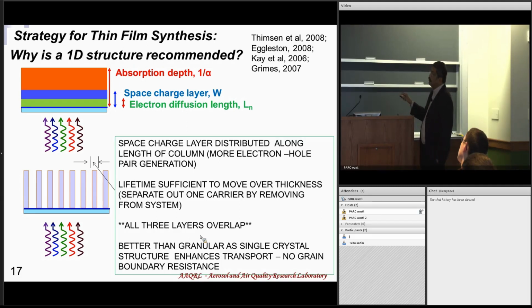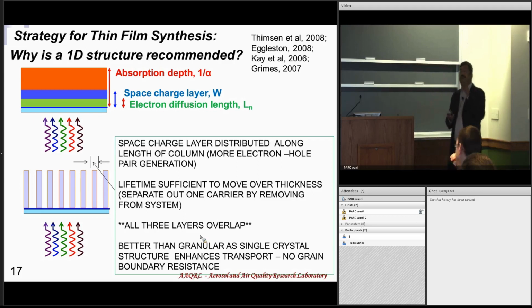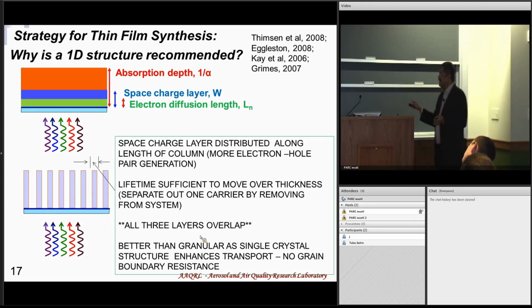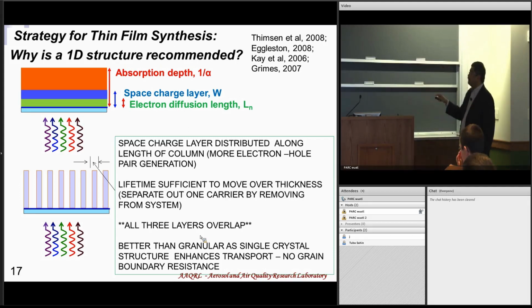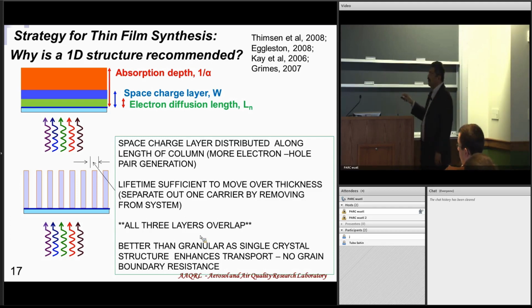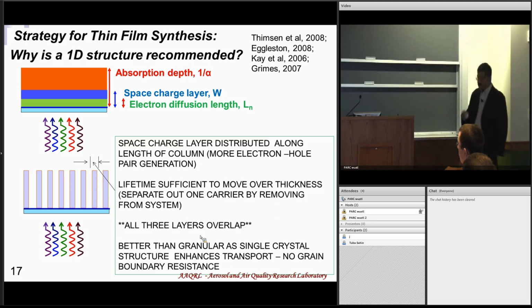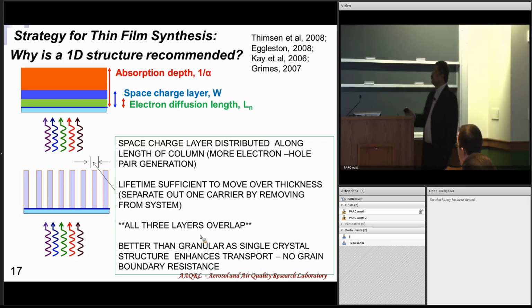Now this is better. You could also have a granular structure. I could have a small semiconducting oxide nanoparticle, but then the electron has to hop from one granule to the other granule, and this creates a resistance or also affects transport, what we call a grain boundary resistance. So a structure like this, which is a single crystal, would not offer that resistance and would allow the electron to be pulled out to the electrode or to wherever you want to then drive it through your load.